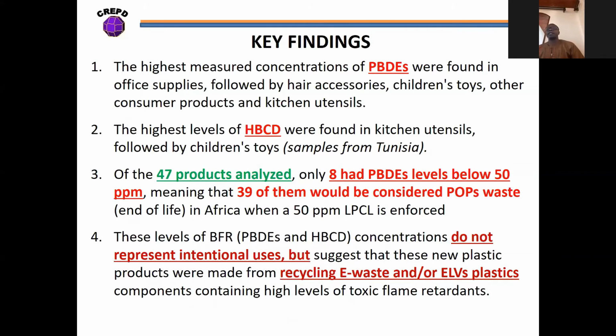Yes, the next slide is about the key findings. The highlight is that the highest measured concentrations of PBDE were found in office stuff, followed by hair stuff, children's toys, other consumer products, and kitchen stuff. The highest level of HBCD was found in kitchen stuff, followed by children's toys in samples from Tunisia.